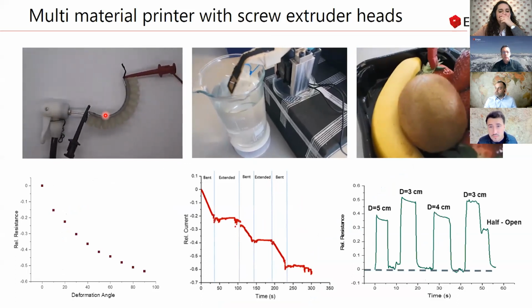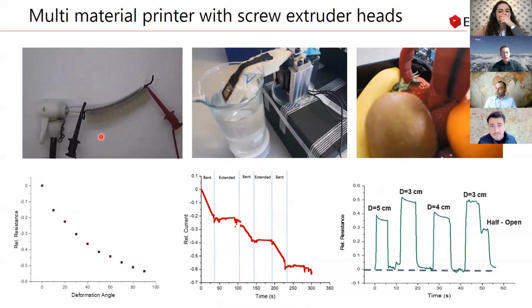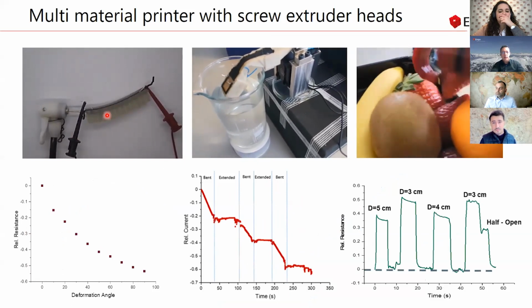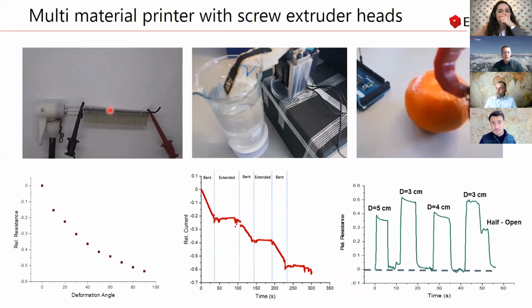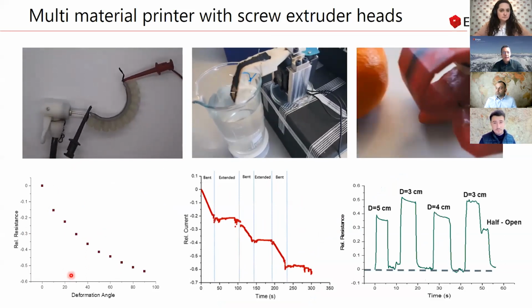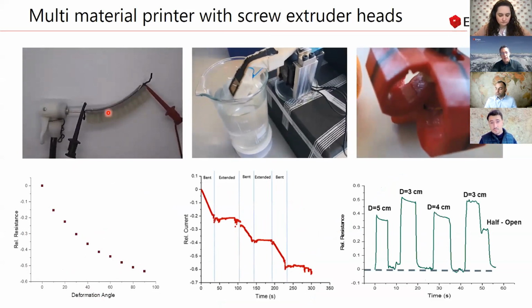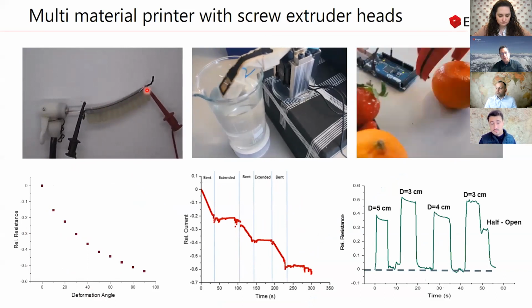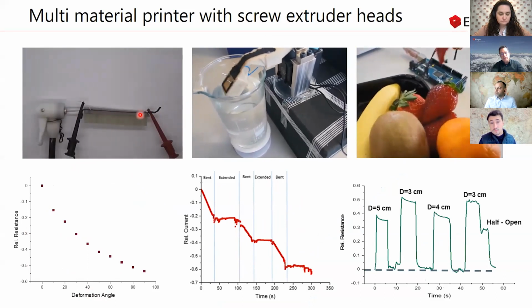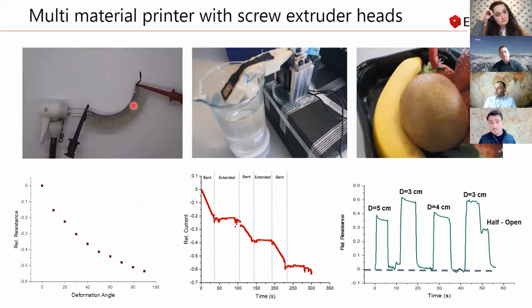So you see here one example for this pneumatic actuator, where you see that resistance changed by changing the deformation angle, which you can measure then with this special piezoresistive strain sensor on top of it.